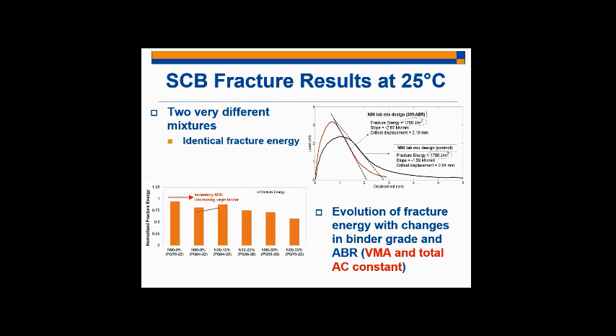So I have here load displacement curves for two very different mixtures. The black curve is our N90 lab-produced mixture, and it's a control mixture. There's no recycled content whatsoever. It's completely virgin. The N90 lab mix design 30% ABR is a mixture with 7% RAS. So you would expect these mixtures to perform differently. I mean, nobody would argue that they would have similar performance. And you can see from the load displacement curve that they do behave differently, right?